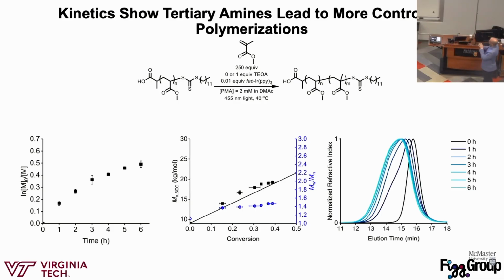Some things to point out, these conditions probably look really weird to you, even if you don't do RAFT polymerization. They are really weird because we essentially had to add in a reducing agent. We're using higher iridium concentrations than usual. This concentration of polymer is about 10 times less than you'd usually run a RAFT polymerization, and we're doing these at 40. So that's where we're really trying to think about how to think about reaction conditions to change the kinetics of the pathways that are going on.